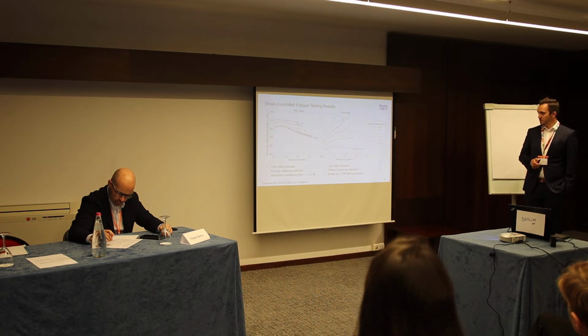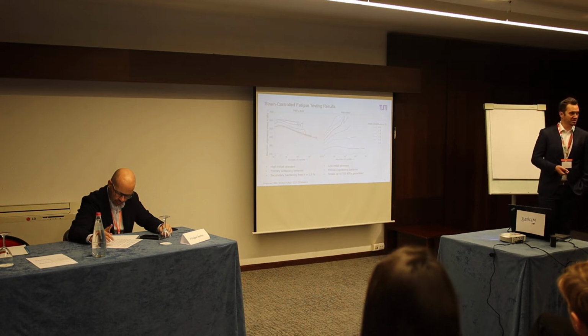The ferrite content here was a bit higher. At least we measured a little bit of ferrite, 0.3%. Also, if you apply it to the Schaeffler diagram, we are a bit more in the area where we have some ferrite. So let's get to the strain control fatigue testing results.